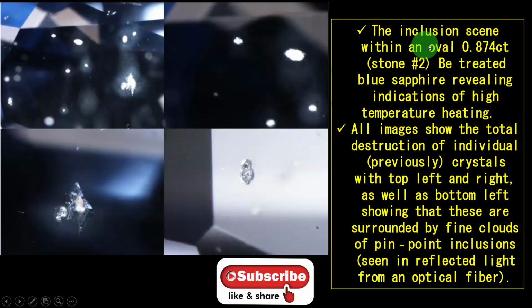The inclusions seen within an oval sample, stone number 2, a beryllium treated blue sapphire revealing indications of high temperature heating. All images show the total destruction of individual crystals, with top left and right as well as bottom left showing that these are surrounded by fine clouds of pinpoint inclusions seen in reflected light from an optical fiber.